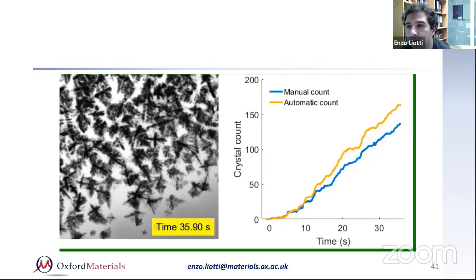The problem with tomography is that it is much more complicated to analyze the data and to carry out the experiment, because you don't have a live view of the image, so you cannot see what happens in your sample while you're doing the experiment. But what we could reproduce here is some kind of case scenario. Because we could control the stirring very accurately, the strength and the direction, we can replicate certain scenarios. So you can do a model experiment and learn from that the effect. It's very difficult to replicate proper casting conditions, but we did some experiments where we were stirring in what we call a vortex. By putting multiple wires and shooting them sequentially, you can create a very chaotic situation, which is that of a casting, for example. The problem then is that your experiment is so complicated that it's very difficult to learn any meaningful data.